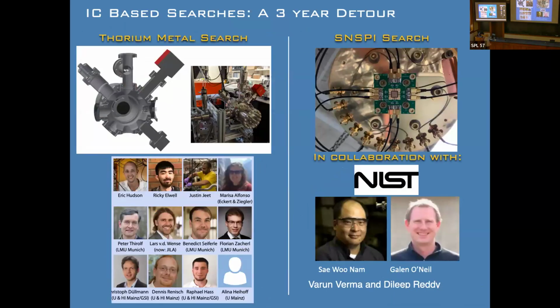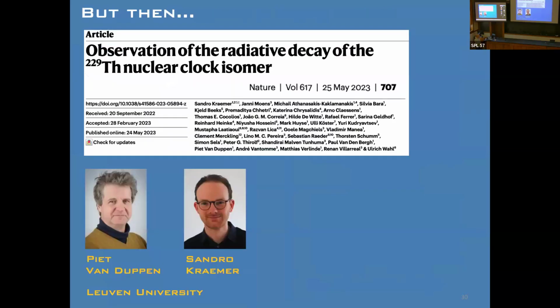So we started a couple of experiments that I'll just flash up because it'll be important later. One was what we call the thorium metal search, in collaboration with Peter and his then postdoc Lars. And then one where we were shooting these thorium ions into these superconducting nanowire imagers built by Sae Woo Nam, who sadly is no longer with us, and Galen O'Neill at NIST. And so we were off doing this, and then in May of 2023, this happened. And this was the key.